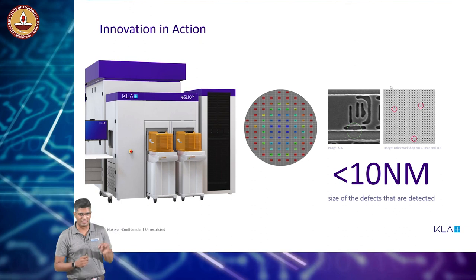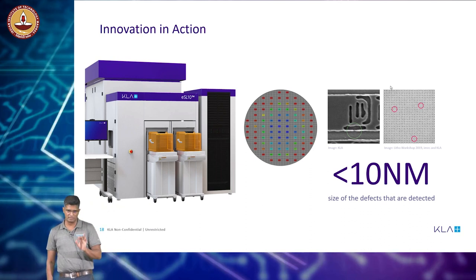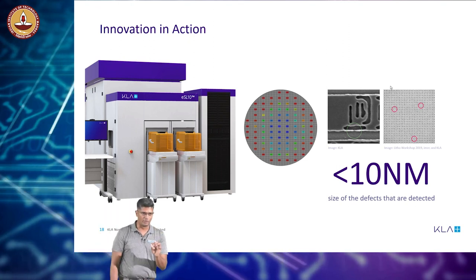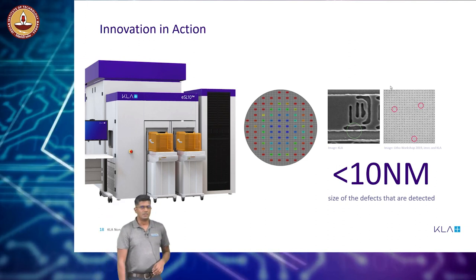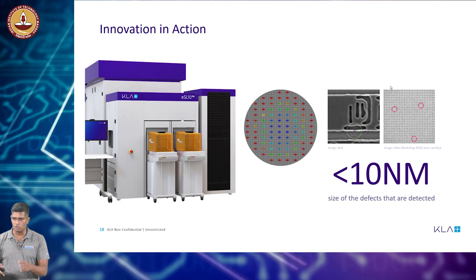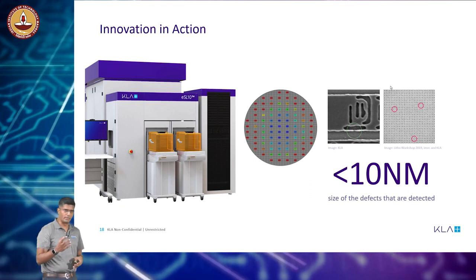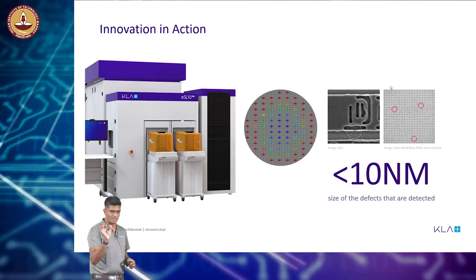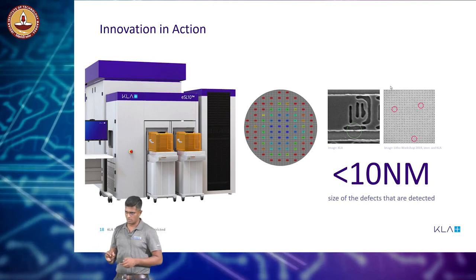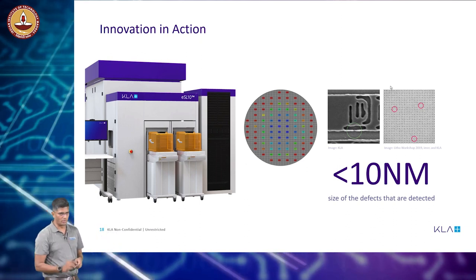These are the kinds of defects we are trying to sift out from 10 billion pixels and 4 petabytes of data, and this happens day in and day out, hour in and hour out. You can imagine the kind of noise filtering we need to do to find these defects, and the amount of processing needed to confirm that something is indeed a defect and not noise. The key innovation we use is optical inspection — a way to take an image and do image processing to find defects. Prior to this, the method used was electron beams, which give 1 nanometer resolution but are about 10,000 times slower than optical tools, whose image resolution is extremely poor by comparison.